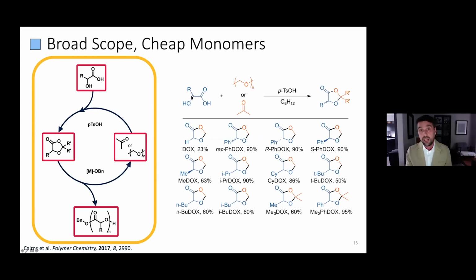to have some chirality here at one of these sites. And whatever chirality I start with, I retain. And so I have retention of whatever enantiomer I use. So if I want to get the racemic mixture, or either the R or S variant of these, I can do this in very high isolated yields. And so I'm going to focus a bit on these mandelic acid derivatives because this is our first commercial